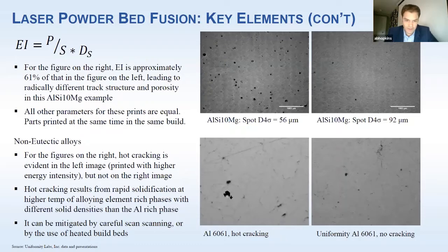And the result is, since it has, I forget if it has a lower or higher density, but a different density than the aluminum, it solidifies, and then the aluminum solidifies because they're different densities in the solid form. Then you get these cracks in your grain structure. And then this material is more or less useless for any structural applications because it's full of cracks.